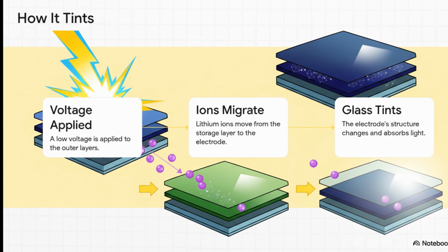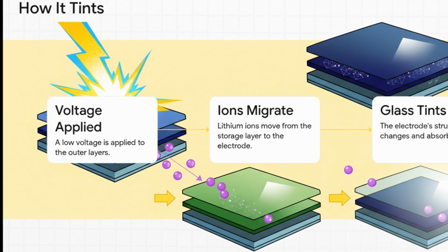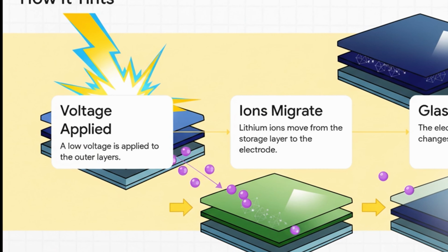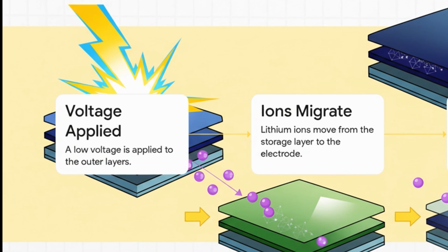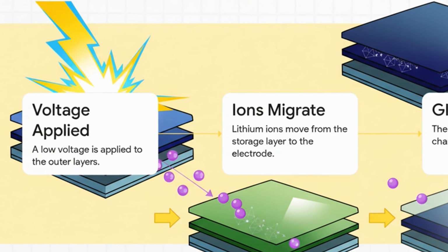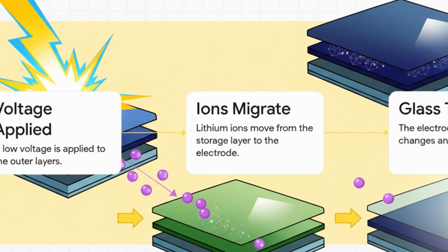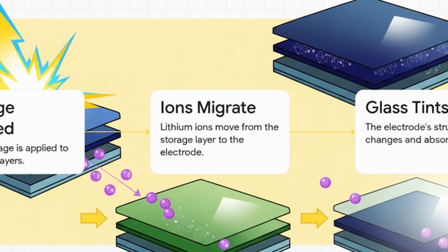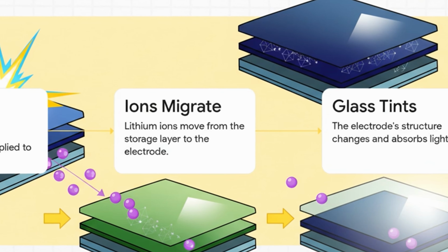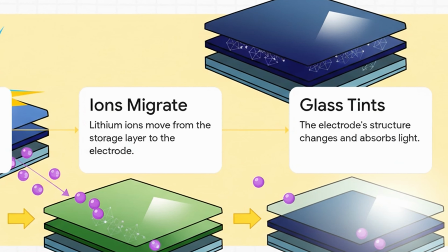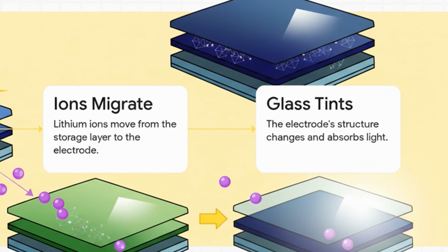So here's how it actually tints. When you apply a low voltage, like a tiny one, these little particles called lithium ions get pushed from that storage layer into the electrochromic layer. This literally changes the material structure, which makes it absorb light and turn dark. You reverse the voltage, the ions move back, and poof, the glass becomes clear again.